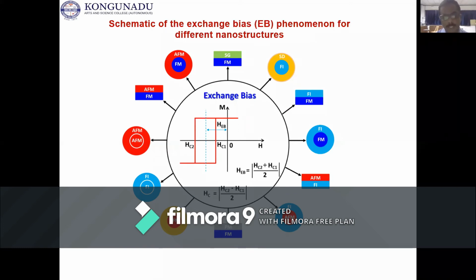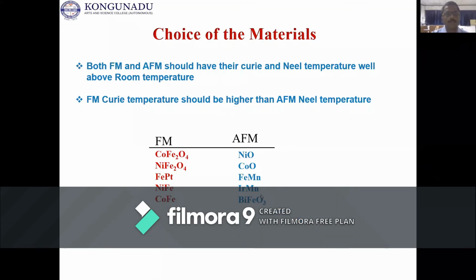Nowadays people are trying to prepare different types of core-shell nanoparticles, which we can use for memory devices in the future. I have given some choice of materials. The condition to choose them is that both the ferromagnetic material and the antiferromagnetic material should have Curie temperature and Néel temperature above room temperature, that is, the ambient temperature. And the second condition is that the ferromagnetic Curie temperature should be higher than the antiferromagnetic Néel temperature. With these conditions, I have chosen some ferromagnetic and antiferromagnetic materials.